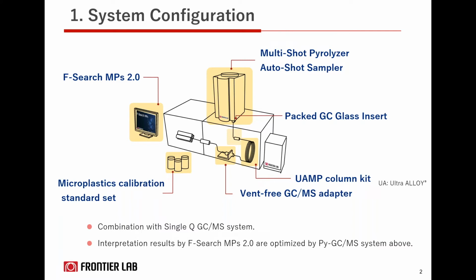You can also see the AutoShot sampler that is on top of the pyrolyzer, and this accessory can automate a continuous series of analysis up to 48 samples. F-search MP 2.0, which is our patented and unique search library that allows you to obtain reliable microplastic identification and quantification analysis. And then, as you learned, we also make the ultra-alloy capillary columns that have superior resistance against bending, heating and contamination due to the gradient multi-layer deactivation process. And also you can see the vent-free GCMS adapter that allows you to quickly switch between the separation column and the EGA tube without venting the MS. And lastly, the microplastic calibration standard set that you can use for creating calibration curve and quantification work.